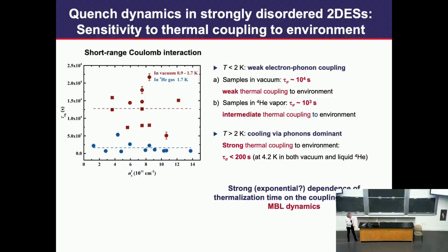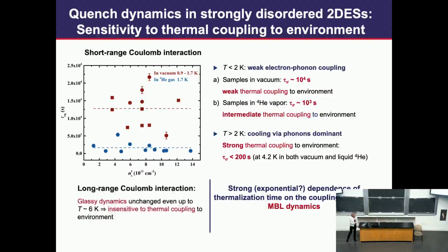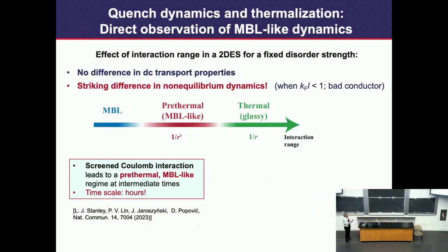This very strong dependence of thermalization time on coupling to the environment is really characteristic of MBL dynamics, in contrast to glassy systems, where in our experiment we did not see any change in the glassy dynamics even at higher temperatures. So basically this experiment showed — and I didn't stress this earlier — that the DC transport properties, or ground state properties, are the same in both the long-range and short-range interaction cases. But there is a huge difference in the dynamics of the system.